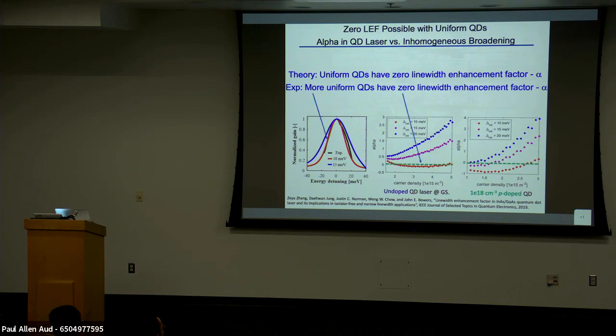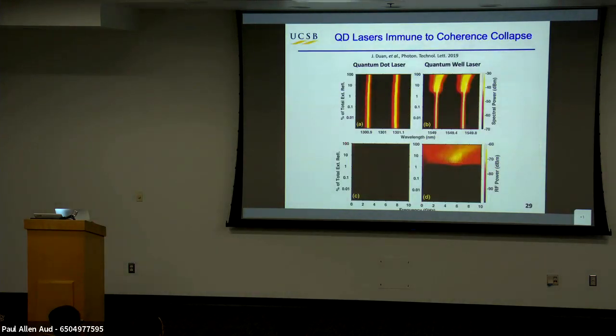So what's the data? The data's here. So look here. This is a quantum well laser. This is just the Fabry-Perot spectra of it. So this is the optical spectra. And up to about 1%, the laser looks kind of okay. But at 1%, this laser has gone completely unstable. It's modulating essentially 100%. It's completely unstable at that point. So you'll see errors way back here, but in the optical spectra, you really see it at about 1%.